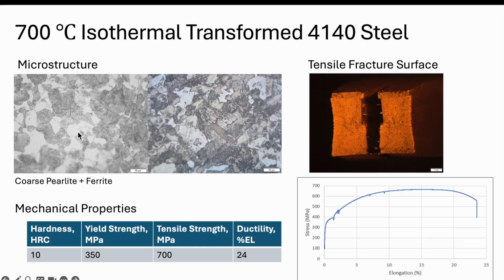And when you look at them, we still see the light regions, so the light grains. Those are ferrite. So ferrite in all of the pearlites. And then for the pearlite, the darker regions, you see more and more of the layers, right? So a lot of layers here, here, here, and also on this other image, you see the layers, right? Because the layers are getting thicker and thicker, or coarser and coarser. And so you can usually see them better when you get up to these higher temperatures. So this is our coarse pearlite, and then the lighter regions is ferrite.